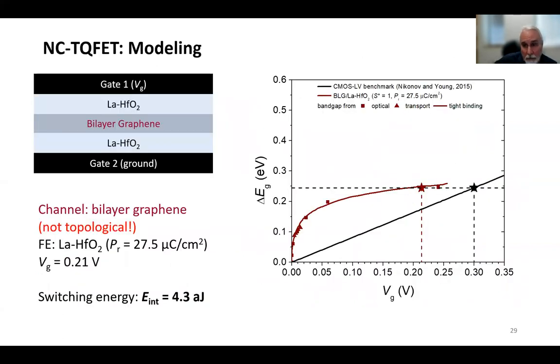And indeed, if one can sandwich bilayer graphene between a suitable ferroelectric, such as lanthanum-doped hafnia, one can achieve bandgap modulation of similar magnitude as CMOS LV, in terms of making a barrier, the barrier height in the CMOS transistor, but at a lower voltage. The switching energy is actually still comparable because the capacitance is a bit higher in this device.